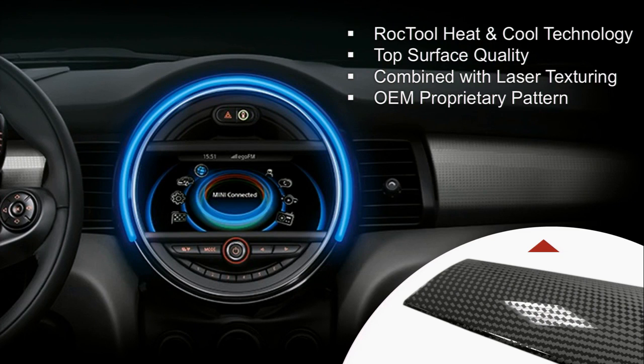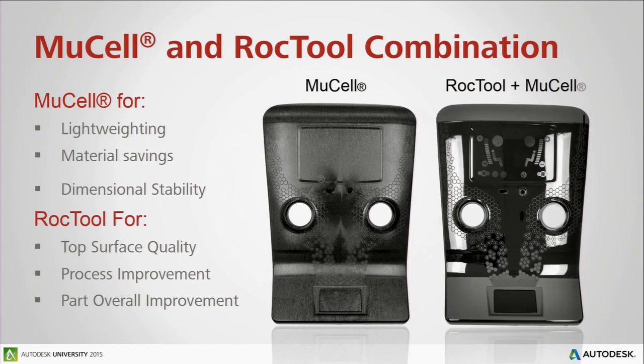So the time we circulate those few samples, last but not least, we have a lot of work with Autodesk to continue developing RocTool. And I know you already spent time on the Mu cell. So that's great, there's potentially synergy here. But whenever you mix plastic with something else, let's say a fiber reinforced resin, short fiber or long fiber, that can be glass or carbon, or a blowing agent or talc or any filler, during that process, when you conventionally mold, the resin and that filler are mixed up and they freeze right away, so they show on the surface. But if you're able to drive the temperature right before injection, the resin at all time, whatever the resin is, will be much faster, will cover that charge, and will have all that filler disappear on the surface.